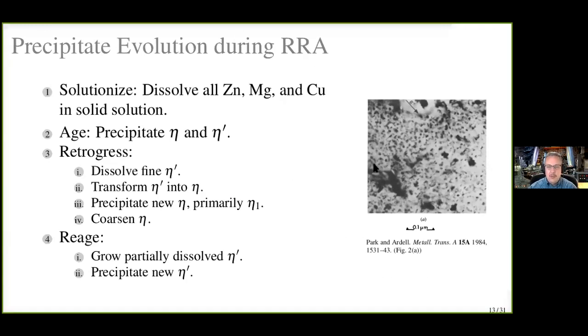So these are what the precipitates look like in a retrogression regime 7075 material. There are two primary categories of precipitates that strengthen 7075. One is an eta precipitate. There are actually three different common varieties of that, and one is an eta prime, which is a finer precipitate that's somewhere between eta and what people may consider a GP zone. So in our heat treating steps, we solutionize and quench, then we age. The aging precipitates out eta and eta prime.